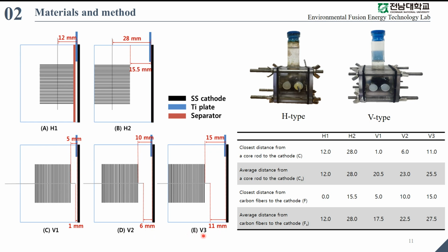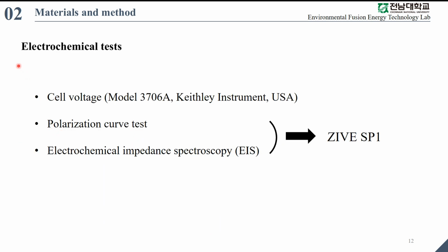The same bioanode was used throughout the experiment. As a preliminary test, a separator effect on power generation was performed in the other anode configurations, and power densities decreased. Since one of our goals was to find the best anode configuration for increasing power production, a separator was not added except for the H1, where a separator was inevitable in order to prevent short circuit. The cell voltage was recorded at 1-minute interval using a system switch multimeter.